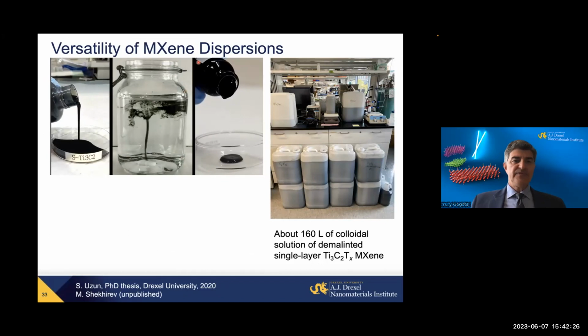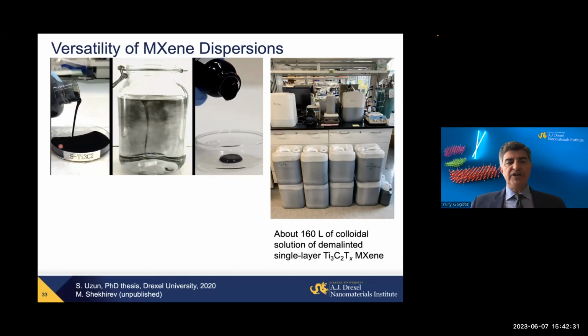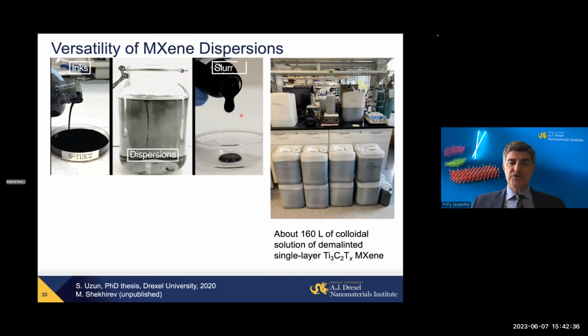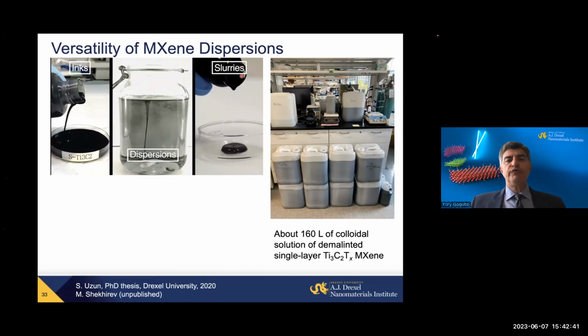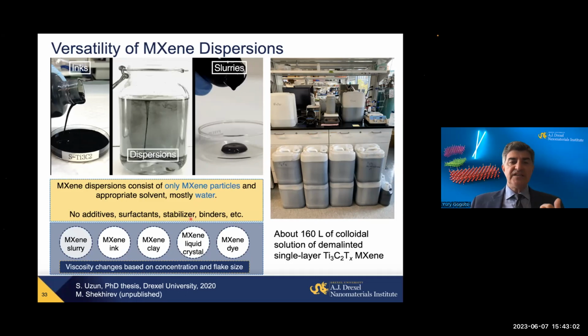We can make dilute colloidal solution for inkjet printing, or liquid crystalline, actually highly concentrated, honey-like solution for doctor blading or for drawing fibers. And here you can see, for example, 160 liters of colloidal solution of MXenes standing in our laboratory. So what's important, and the message from this, is that this material is highly scalable. The process is scalable. And we can make MXene dispersion again just in water, which again means we don't need to burn binder after printing or anything else.